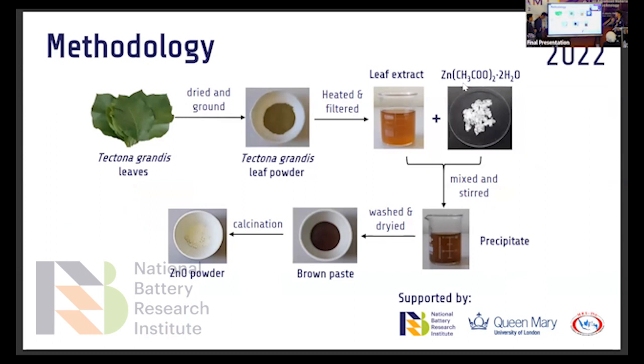This is the methodology. The Tectona grandis leaf we dry and grind into a powder. The powder we heat and filter with distilled water. The distilled water has the leaf extract, and we add zinc acetate. We mix and stir, and we get the precipitate. The precipitate we wash again and dry until we get a brown paste. The brown paste we calcinate until we get ZnO powder.